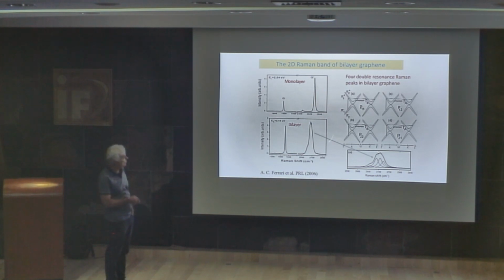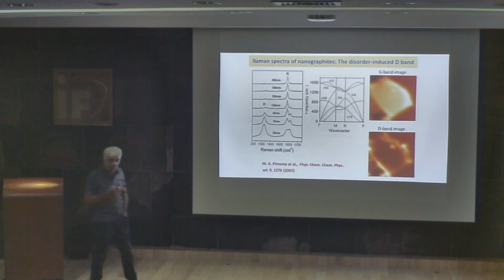Then the shape of the band is very useful to distinguish the number of layers. If I have 1 layer, 2 layers, 3 layers, by the shape of this band we can get information about the number of layers. Okay, another important thing in graphene is what we call the disorder-induced band. For example, here I have the spectrum of many different samples of graphene with different sizes. When I have a very big sample of graphene, I only have the G band. But when I have a very small sample of graphene, like this one that is 20 nanometers, two new peaks appear, one here that we call D, and another here that we call D prime.